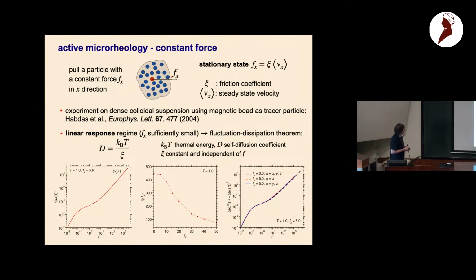Okay, first of all, what do we expect in the linear response regime in this case? So we pull the particle with the constant force, and we obtain, after some time, a stationary state where we see a constant velocity of the particle. So F is proportional to the stationary state, steady state velocity, and this proportionality factor is the friction coefficient. Actually, a similar experiment has been done with magnetic beads a long time ago by Habdas et al., in the Weeks group.